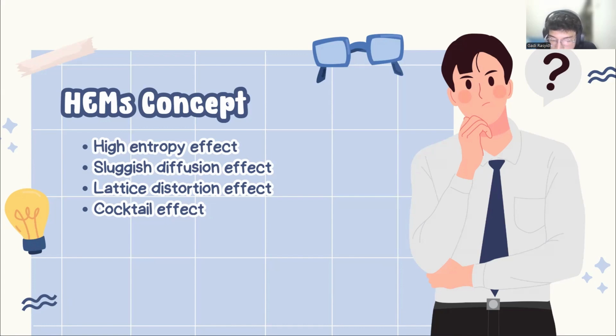The first perspective attributes it to the random atomic arrangement in high entropy structures, leading to variation in atomic behavior during vacancy transition between neighboring atoms. Different atoms adhere in different ways, leading to a local energy difference in the lattice. Research by Tsai indicates that energy differences cause atoms to diffuse more slowly, with atoms spending 1.73 times longer at low energy sites than at high energy sites, resulting in the sluggish diffusion effect.